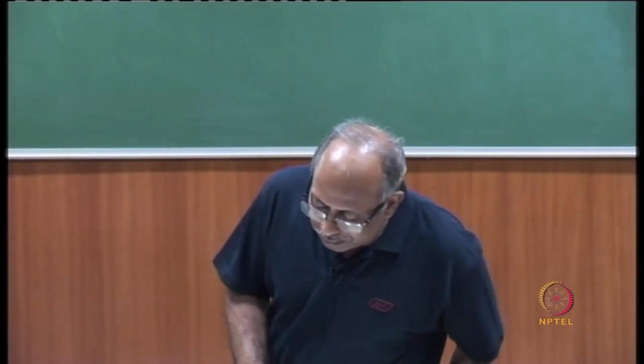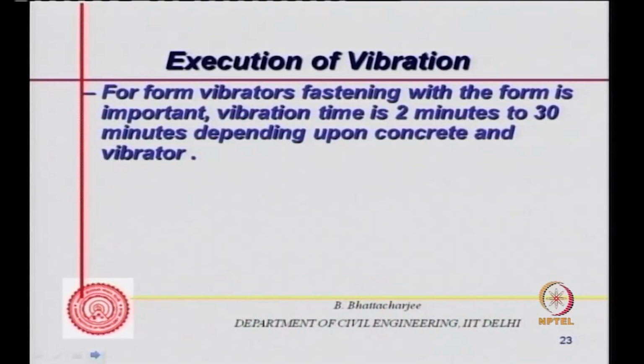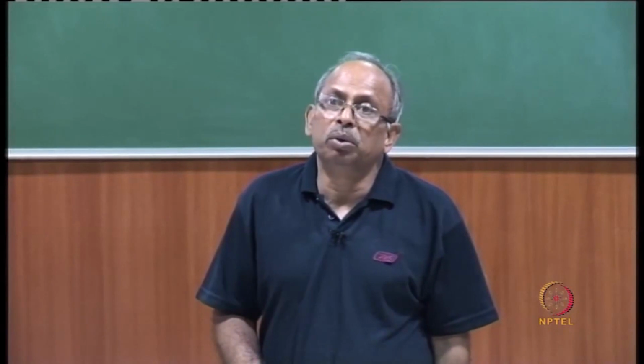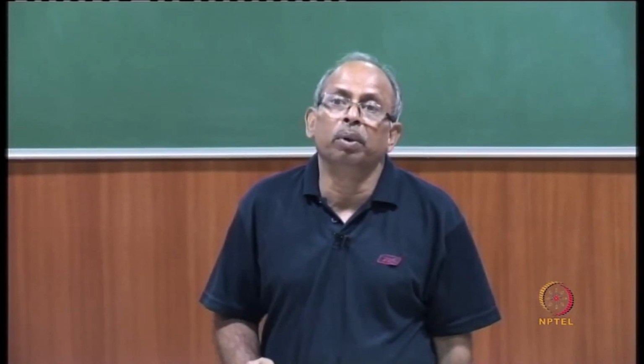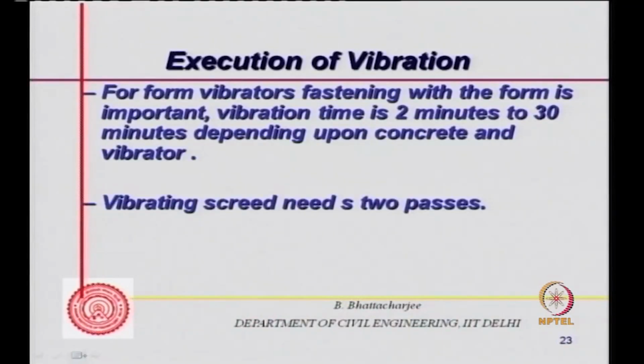For, of course, shutter vibrators, which are fastened with the form, vibration time is 2 minutes to 30 minutes depending upon the concrete and the vibrator itself. So they require a longer period of time, more energy. Screed needs, of course, 2 passes.